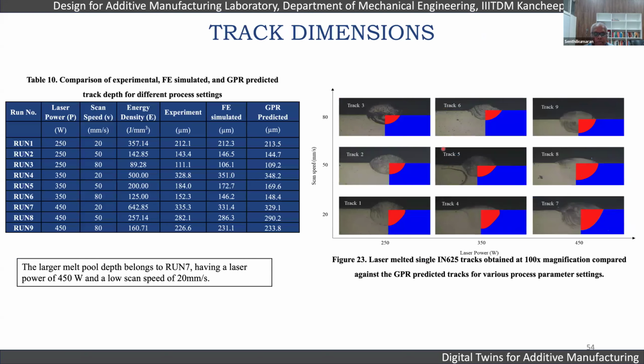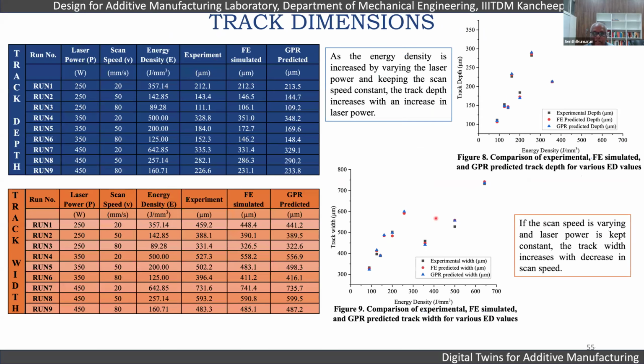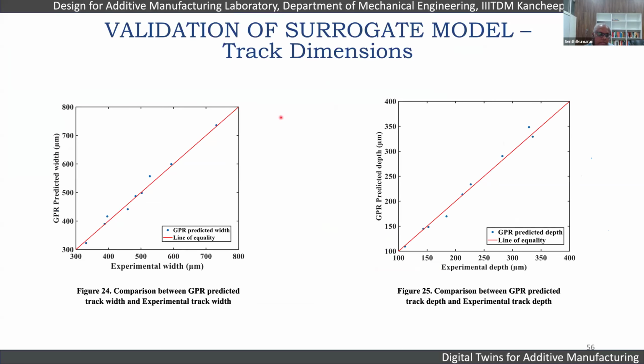So we were also able to get the track dimensions to pass on to coupled thermomechanical simulations. Based on the solidus and liquidus lines, the GPR predicted width and track heights can be predicted. We have seen finally that the FE predicted, the GPR predicted and also the experimental depth are closely correlated here, and the error is much less. You can see the line of equality: the GPR predicted width along with the experimental width is falling in line with the line of equality, and for the depth and for the width, we are able to predict more accurately.